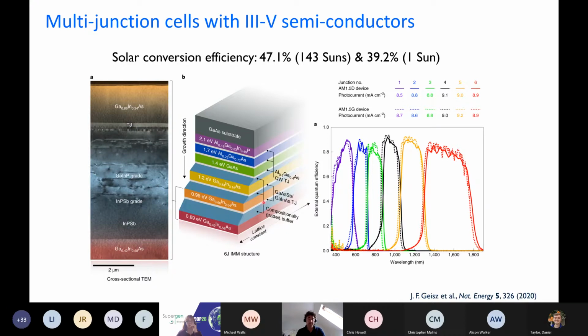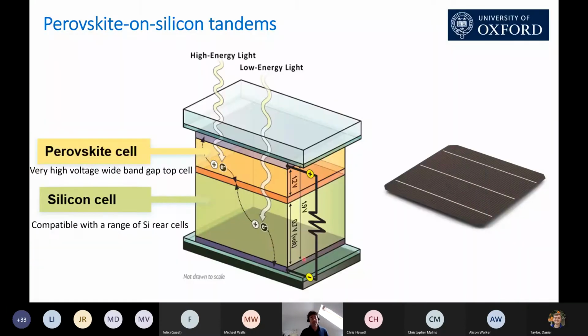Perovskites, on the other hand, can be tuned. We can tune the composition of these materials to actually make the band gap not quite go as low as some of these materials here, but certainly cover most of this spectrum in the near infrared to visible region, which means they could actually be suitable for tandem or multi-junction cells. And one of the simplest embodiments is to put a perovskite cell on top of a silicon cell, so not to compete with silicon, but to actually augment it in a so-called perovskite on silicon tandem device. And this requires the perovskite material to absorb about half the sunlight, so it just absorbs the visible light, and then the infrared is transmitted through the perovskite into the silicon.